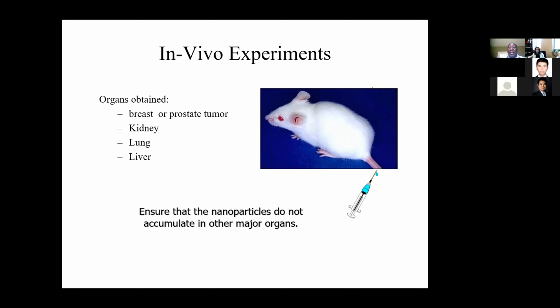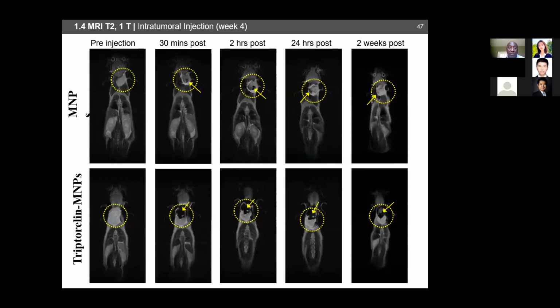And then at that point, you let that tumor develop, usually for between 14, 21, and 28 days. And then you can inject nanoparticles into the mouse to enrich the MRI images, or you inject drugs to shrink the tumor. So here's some results for the injection of nanoparticles. What you see is that when the nanoparticles are conjugated to LHRH, you get a darkening of the tumor in T2 contrast, which enables you to image the tumors at an early stage. The resolution we see here will enable us to do submillimeter imaging in ways that contribute to clinical cancer detection.